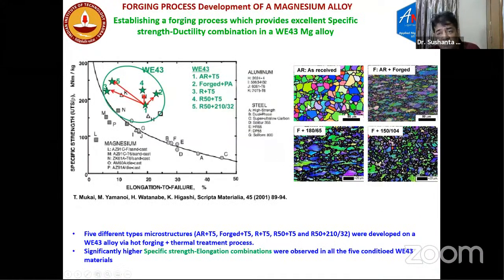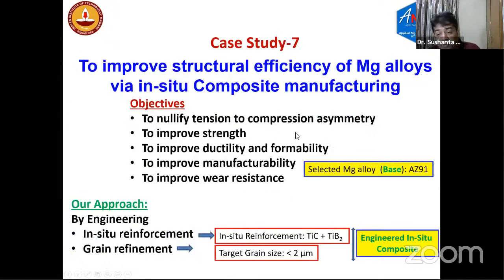We also established manufacturing processes for different forging processes of magnesium by engineering different kinds of microstructure. We established the forgeability improvement of magnesium, and here we try to improve the structural efficiency of magnesium alloys via in situ composite manufacturing. Here our objective was to nullify tension to compression asymmetry, improve strength, improve ductility, improve manufacturing, improve wear resistance. We selected a parent material.